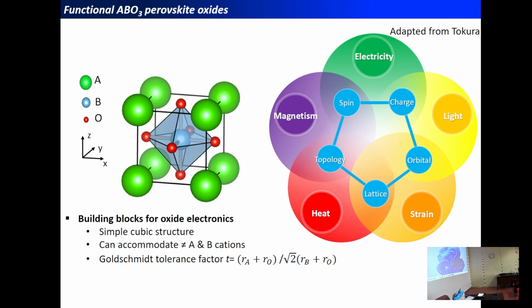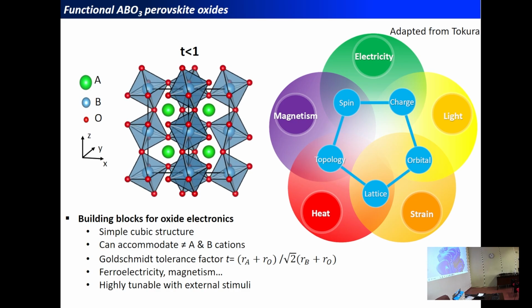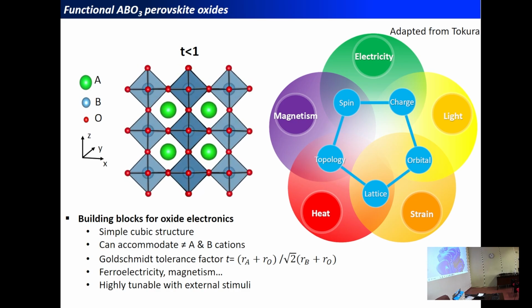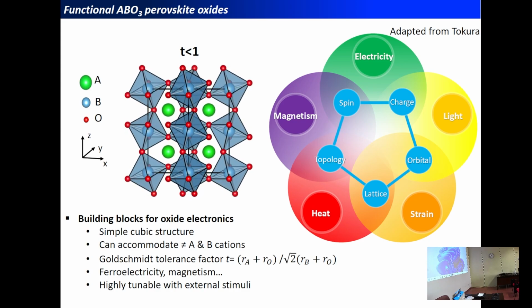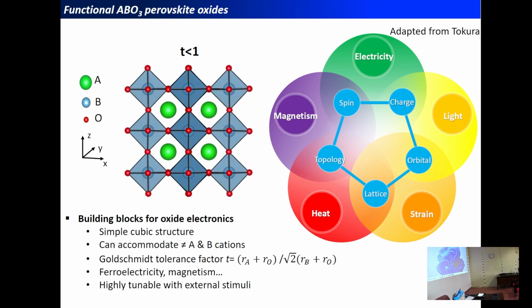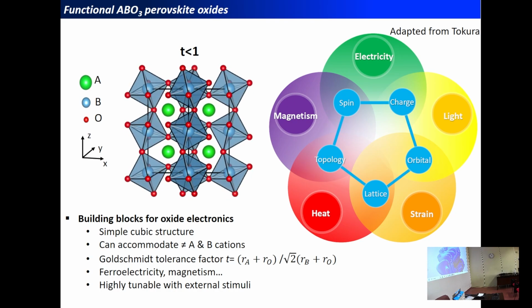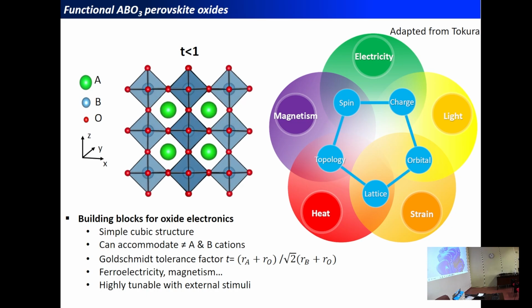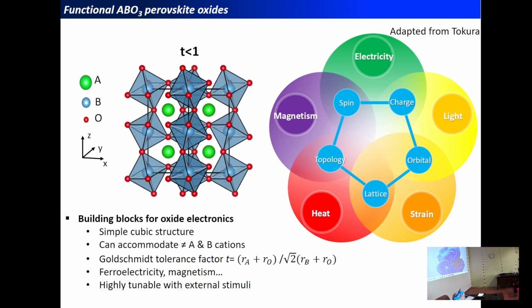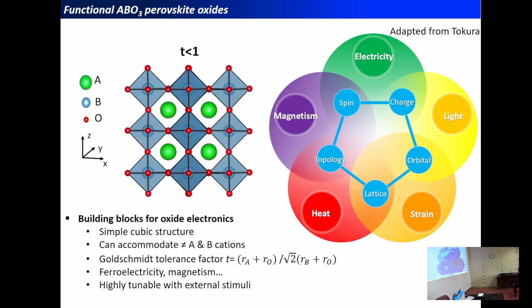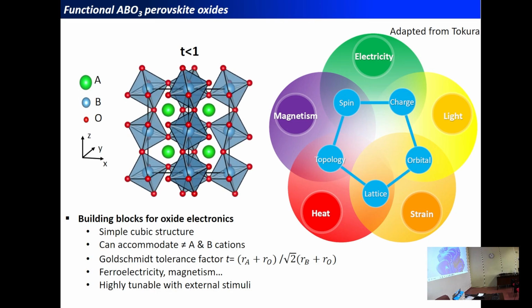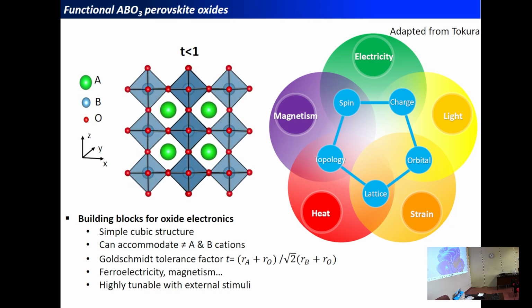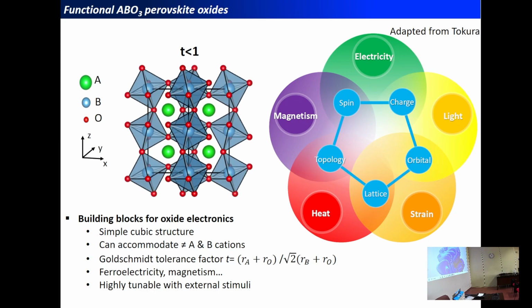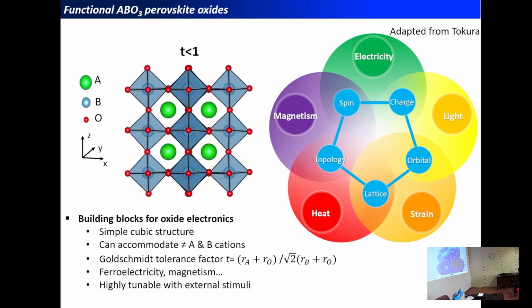Depending on the orbital filling of these cations, but also on the relative cation size mismatch that we can estimate through the Goldschmidt tolerance factor, it can give rise to numerous structural distortions, such as the ubiquitous octahedral rotations in perovskites. When the tolerance factor is lower than 1, which corresponds to the perfect cubic system, as the A-site cation becomes smaller with respect to the B cation, the material will show octahedral rotation.